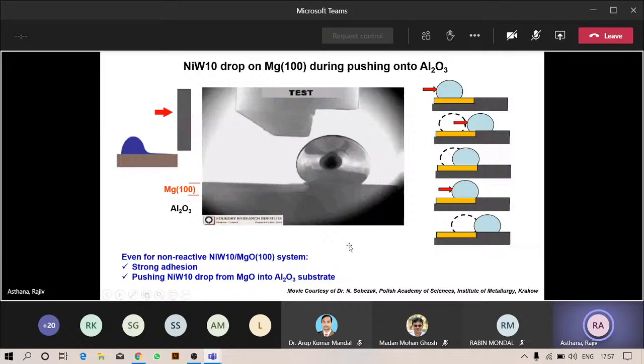Other things we are looking at are basically some interesting things in a system like nickel tungsten droplet on magnesium oxide. You see some kind of a fluctuation in contact angle. Basically, the metal droplet will dance and change its contact angle during spreading. And that is because the droplet will interact with magnesium oxide, and it can form really small, teeny microscopic bubbles from reaction. And those bubbles will cause the droplet to change its shape, which shows up like the dancing droplet.